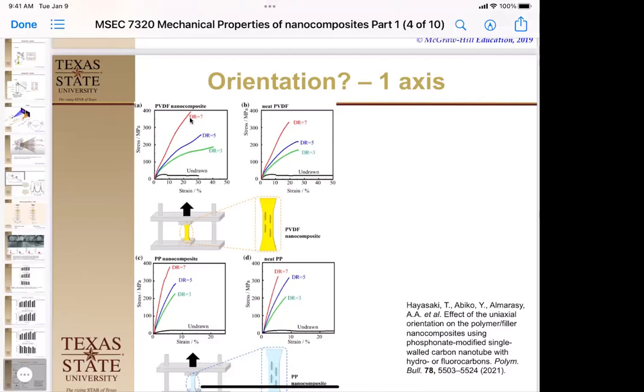Okay. So then let's say, maybe it's the polymer, the polyvinylidene difluoride. So let's try with polypropylene. Do the same compound, do the same undrawn strength. You see both of them still have low modulus. And in all 3 cases, as we draw and order the polymer, it increases in strength. But as we draw and order our nanocomposite as well, it increases even more. So that's a 10% gain in modulus in 2 different polymer systems using the same drawing method. And that is with a phosphonate-modified single-walled carbon nanotube.